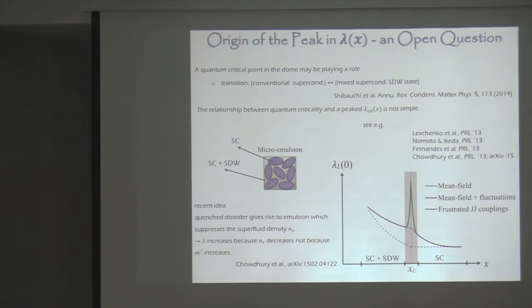So the nature of this peak is still debated. People talk about a quantum critical point existing at near optimal doping, where you are transitioning from the right. If you go in from the right, from a conventional superconducting phase, and then on the other side there's a mixed state, a superconducting spin density wave state. So maybe there's a quantum phase transition between these two states.